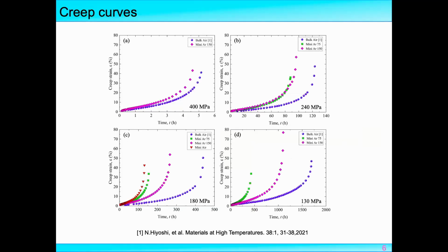The creep test result is given here for the blue point. This is the creep result tested using standard specimen obtained by Professor Hiyoshi at the University of Fukui, Japan. From this figure, we can see that at high stress level or shorter rupture time, the difference is not so large. However, with the decreasing of applied stress, the gap between standard specimen and the miniature specimen increased. Moreover, we can also see that at relatively low stress level, the air flow also affects the creep life. For example, for this case, with high air flow, the creep life is longer than that with low flow condition.